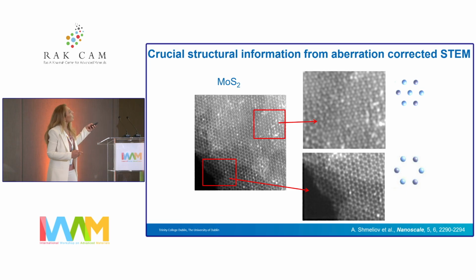So when you see bright atoms in your image, you don't need very cumbersome, very difficult interpretation. The intensity here scales with the atomic number of what you are detecting. So heavy atoms will show bright, lighter atoms will show darker. Actually, this is one of the first works that we did with molybdenum disulfide, and we learned a lot. We learned from this what to use these materials for.